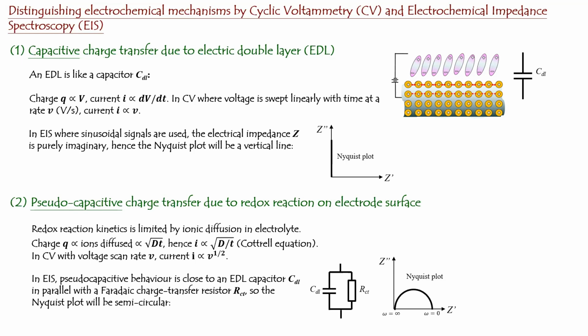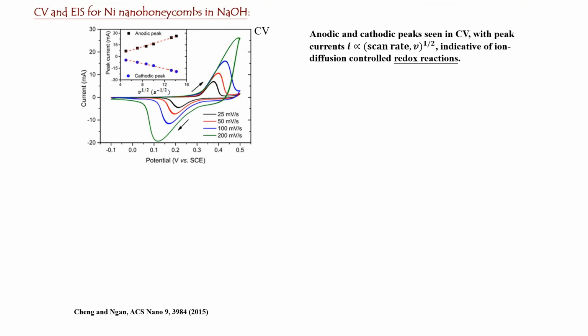On the other hand, if you have the redox reaction, that's what people call the pseudo-capacitive charge transfer. The usual electric circuit for redox reaction is a resistor in parallel with possibly also this EDL capacitor. So if you look at the Nyquist plot, the complex number plot of the impedance, you should see a semicircle. Okay, all these are just control theory, year 2, year 3 control theory in universities. That's the CV, that's the cyclic voltammetry.